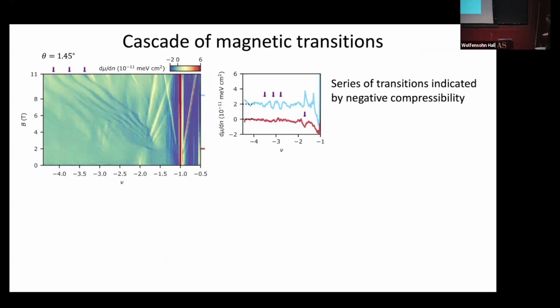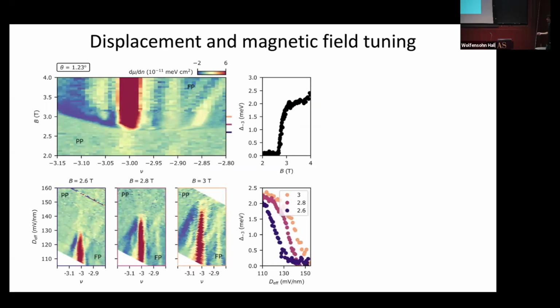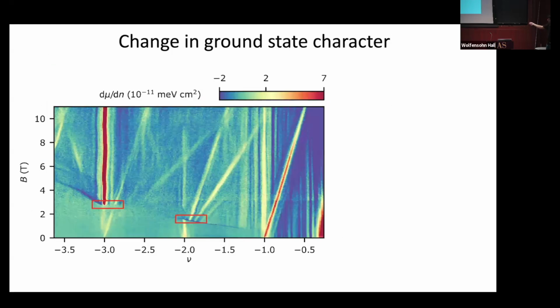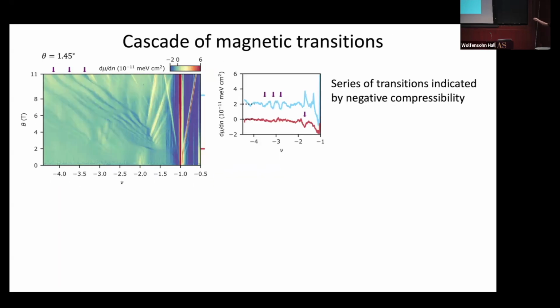And the last thing that I'd like to say is that we can use Maxwell relations to go from our inverse compressibility data. This is a measurement at 1.45 degrees. If I go now to higher magnetic fields and higher filling factors, you can see that there's a series of these dark blue features that are cutting diagonally across. These negative compressibility features are signs of phase transition. So you saw that here, that there's a strong dark blue feature at these spin transitions. So the same is true for these transitions here.